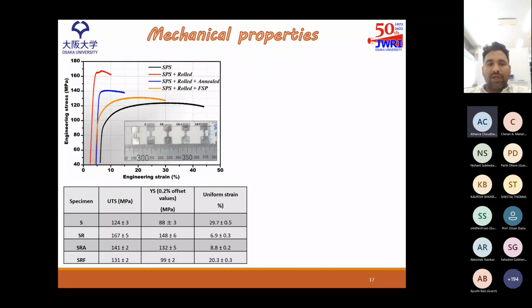Coming to the mechanical properties, we have observed that the rolled specimen shows very less ductility with higher strength, whereas the spark plasma sintered specimen, because of its large grain size, shows higher elongation, but the strength is very less. So what we say, intermediate properties are obtained in the SRF specimen, with sufficient ductility as well as higher strength.